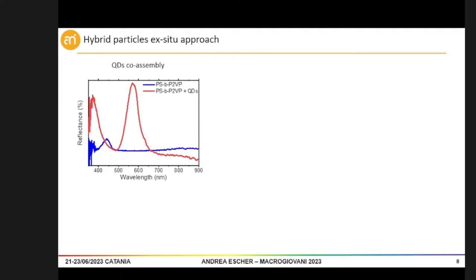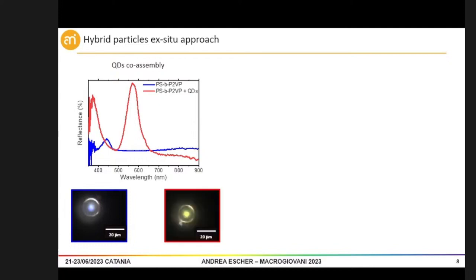Also for this case, I want to report the preliminary results, and in particular we have this reflectance spectrum. The blue spectrum is the one without quantum dots inside, and we can see that the photonic band gap peak is located between 400 and 500 nanometers. After the formation of the quantum dots, the photonic band gap shifts to higher wavelength, located more or less at 600 nanometers, and we also increase the reflectance of this sphere. Also for this case, I report the two images, the one without quantum dots and the second one with quantum dots inside.